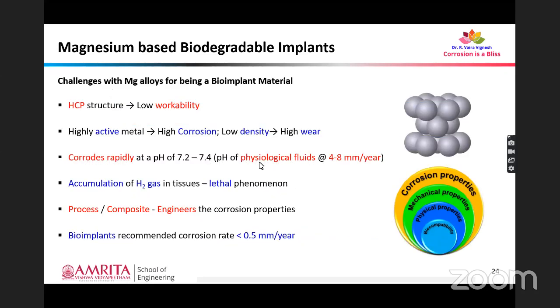However, there are limitations with magnesium. First is their HCP structure. The HCP structure limits the workability of magnesium alloys. And magnesium, as we have discussed already, is a highly active metal that results in a high corrosion rate. And the low density of the material results in a high wear rate too.